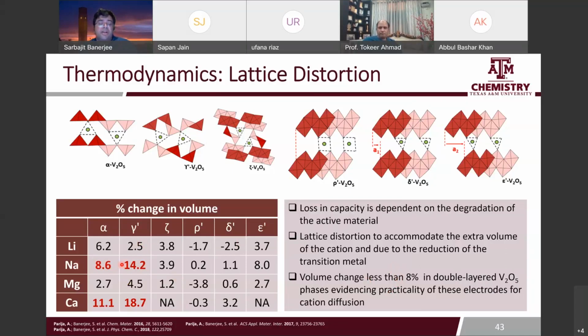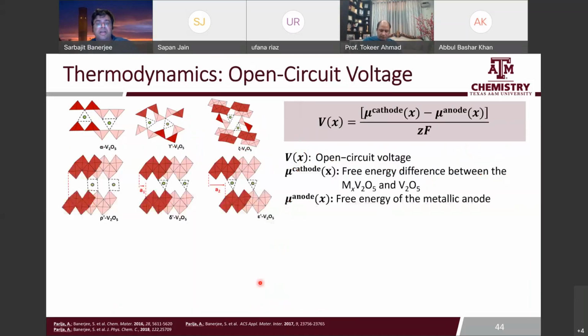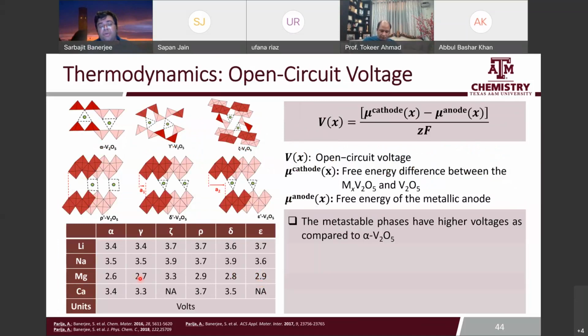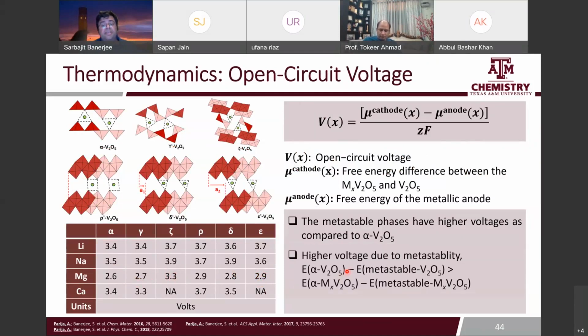And sodium ion, because of the large size, is notorious for large volume changes, and this has been a real challenge in trying to incorporate sodium ion batteries. And this is also true for calcium ion. But as you can see, across these structures, magnesium ion can be accommodated with relatively small changes in volume. The second thing to consider from the thermodynamics is the voltage. And the voltage, again, for magnesium is a little bit lower than lithium. But by going to a metastable phase, you can access a slightly higher voltage. And that is directly a result of the metastability. Therefore, we can get higher voltage on the order of about 3 volts.